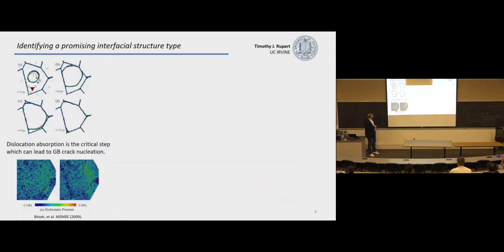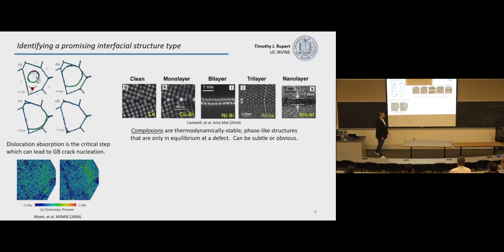This is just showing sort of why that might matter. Another nice example, this is from Eric Bitzek's group. They were trying to isolate this dislocation absorption event. They added a dislocation artificially, strained it, let it go and be absorbed, and we're finding these high stress regions at the boundary, which is where cracks were going to form.